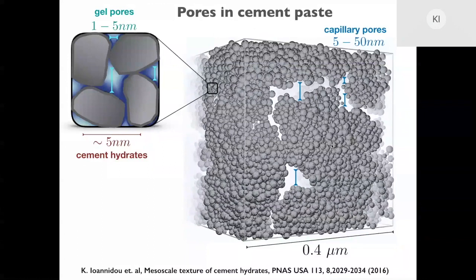These are the gel pores, the ones you see on the left in the zoom in, which are pores of 1 to 5 nanometers that one finds in between the close-packed cement hydrate grains. And then we have the capillary pores, which are pores between 5 and 50 or even larger, 100 nanometers, that one finds on the way that these grains are forming clusters and aggregating into larger structures.